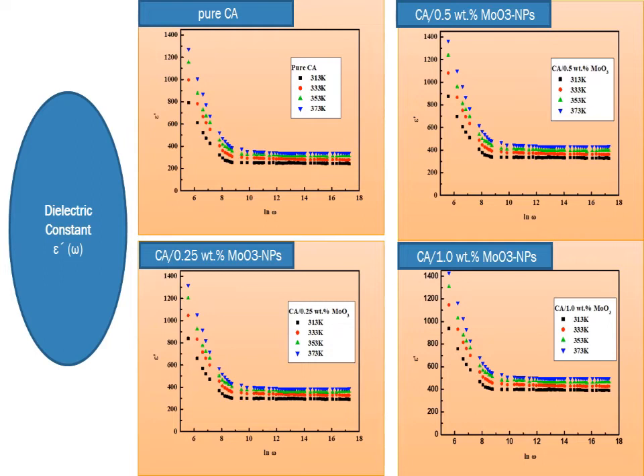This behavior, in which the dielectric constant is high at low frequency, can be due to the interfacial polarization, and at larger frequency it was due to Maxwell-Wagner-Sillars polarization.